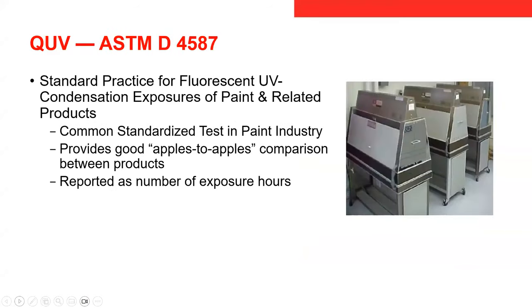And then QUV is another accelerated test, and this is a standard practice for fluorescent UV condensation exposures of paint and related products. This is a very common standardized test in the paint industry, and it provides, as Mark has mentioned a couple times, an apples to apples comparison between products, and it is reported as a number of exposure hours. So that's why we showed the chart earlier, because it gives you a good idea of how South Florida, EMMAQUA, and QUV all correlate to each other, because they are reported differently.